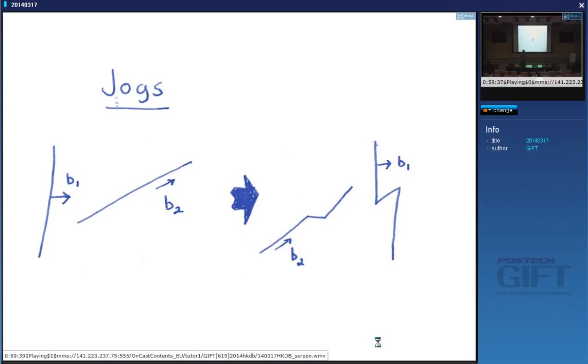but that also means that the line on which the dislocations lie must be perfectly coherent. Because if it is not perfectly coherent, then you need another set of dislocations. So the fundamental principle for martensitic transformation is that you must be able to find one fully coherent line between the parent and product lattices.